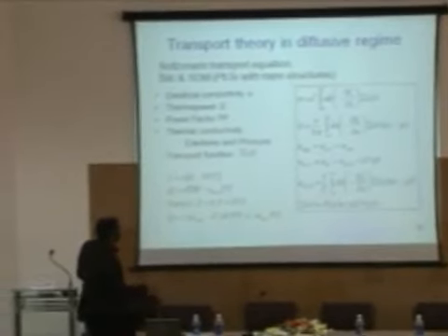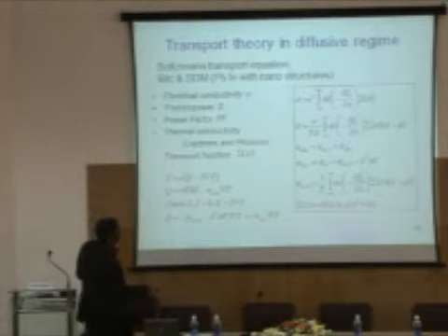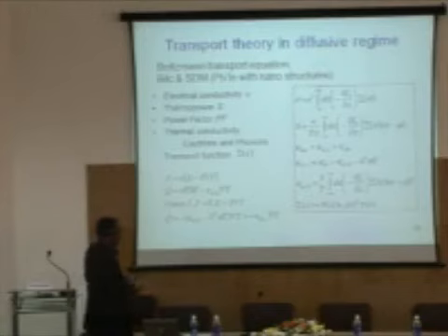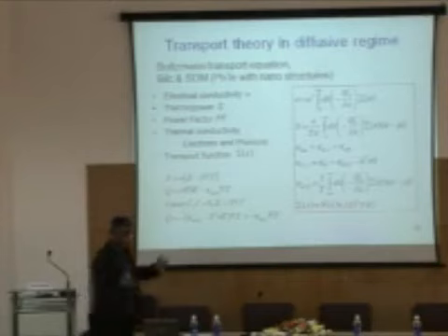Because experimentally this is what is used, and I told you that to get a perfect thermoelectric, I must make this 0, which means these two guys perfectly cancel. So what is the physics such that these two guys will perfectly cancel? Then my electronic thermal conductivity at constant current is 0, and I get the best electronic thermoelectric.